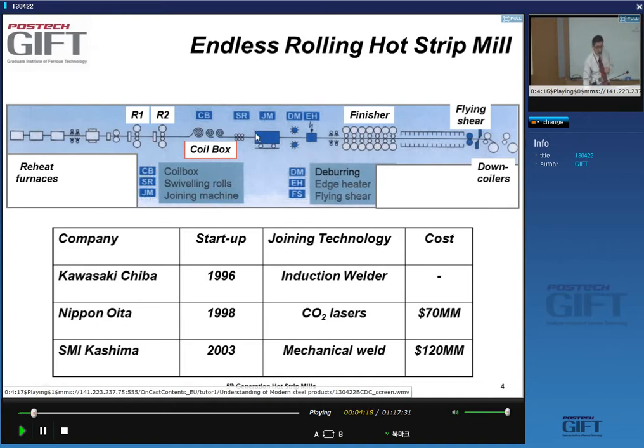Because this joining machine that you see here is in operation while the bar is being rolled, right? So it needs to move with the end of the bars. Plus, of course, you need to prepare the strip so that the bar edges are easy to weld. Yes, it has to have the right shape. And then, obviously, after welding, any surface irregularity has to be taken care of. You have to flatten it so it doesn't give you instability during rolling. And also, this edge of the bar has to be deburred and everything prepared for the welding.